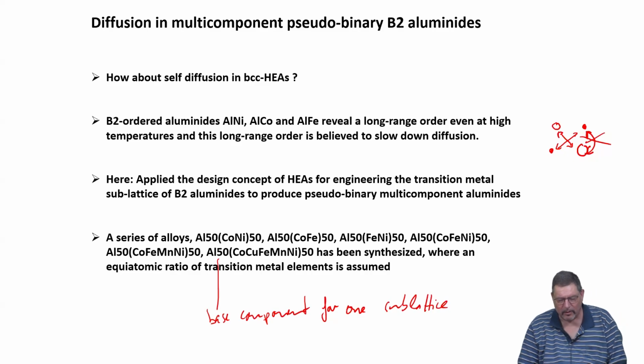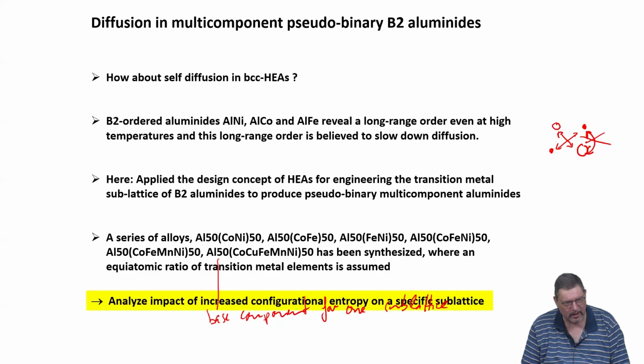And we have then on the second sublattice anything from binary to quaternary to ternary and also to 5-component systems. So we replace cobalt and nickel by cobalt iron, iron nickel, then we have all the binaries, then we go for cobalt iron nickel ternary, then we add manganese, and in the end add also copper. We want to check how this configurational entropy increases on a specific sublattice.